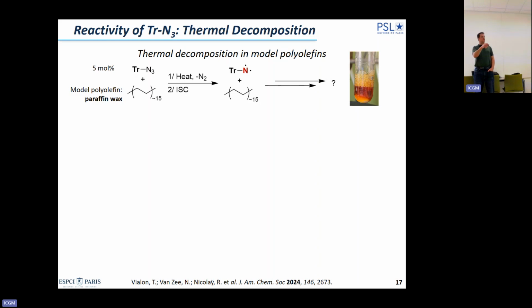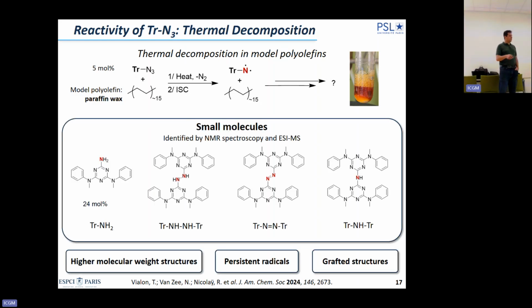We loaded it a lot so we can see what is taking place. We don't want to put that much additive later on the polymer. And we heated this and we studied what is taking place. And what we saw, I will go fast on this one, is that we formed small molecules, aminotriazine, for example. We formed also the azo compound, the hydrazine type compound, and also amino ether bridges. So a lot of different things. So it's not a selective reaction.